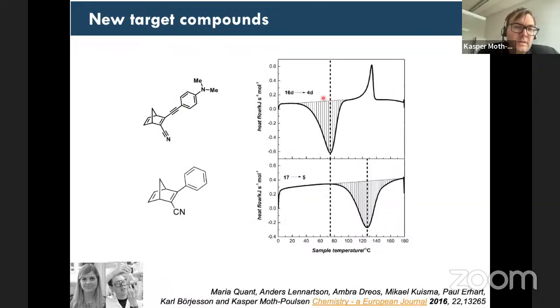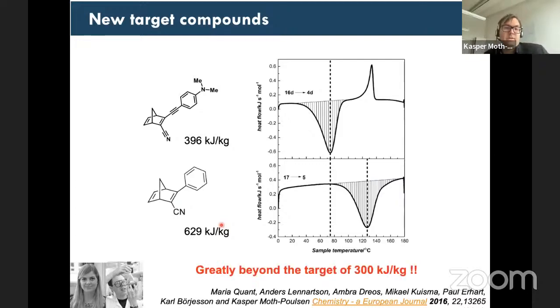We could measure the energy storage density using an instrument called a differential scanning calorimeter. We measured how many joules per gram are stored in the molecule. And with these 2 molecules, we had actually almost 400 kilojoules per kilogram and 629 kilojoules per kilogram. So these are much more than the original target of Yoshida, and this is coming about from the use of a very small acceptor and the donor and acceptor on the same side of the molecule.